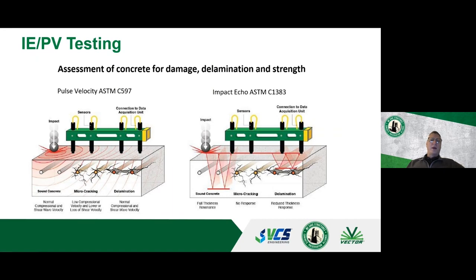Every time that wave encounters a crack, which is essentially a void, it will impact the speed at which that energy wave is traveling. So as it impacts that wave, the sensors are measuring that, and you're able to get like a 3D image of how that's impacting, how deep those cracks are, how wide those cracks are.